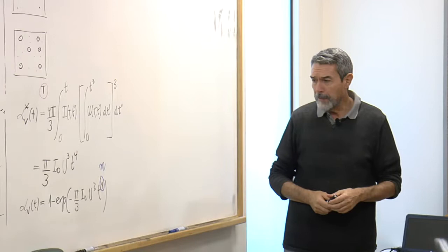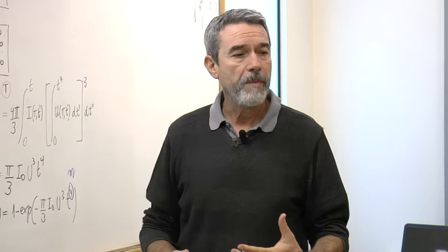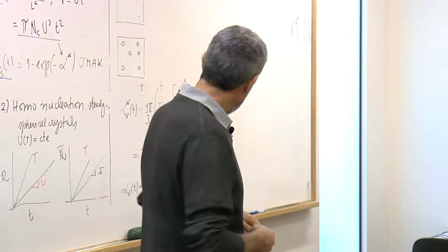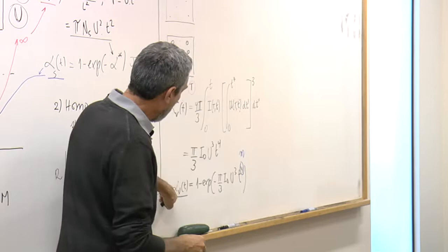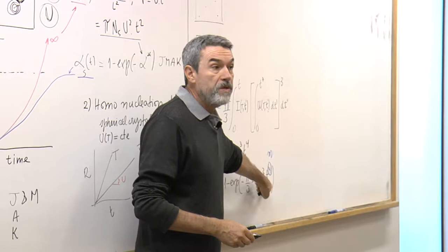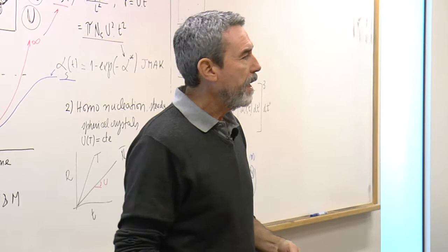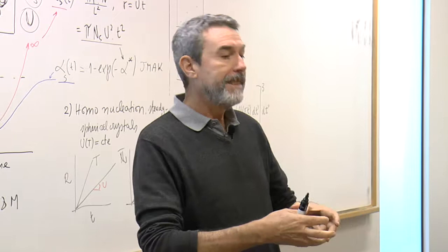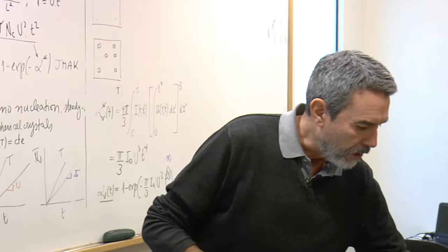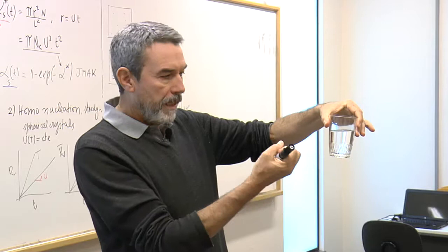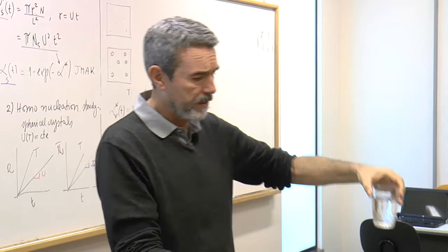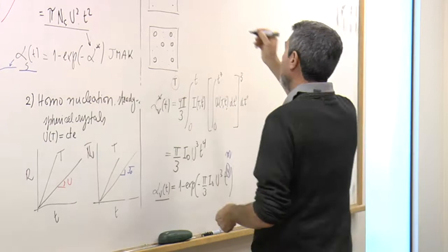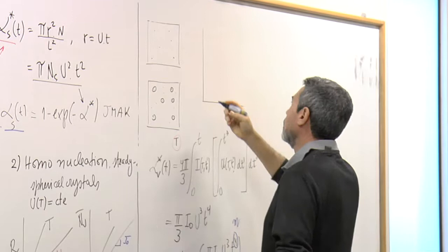And many people, when they're studying the phase transformation of any material, what they normally do is to measure alpha versus time. So you can use optical microscopy, electron microscopy, X-ray diffraction, DSC methods. You can measure the density of the system. So I'm talking about a problem where you have a glass piece, heat treat this glass piece, and follow the evolution of crystallization with time. This is the overall crystallization. So experimentally, one can then produce a plot like alpha v versus time